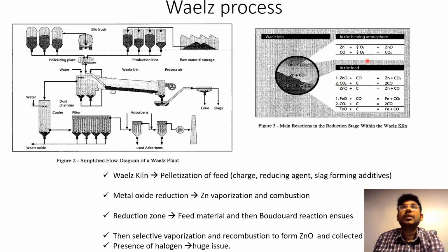With the temperature set around 1250 degrees Celsius, not a lot of other metals are going to be melted. So you have some formation of metals: zinc, lead, I think silver, cadmium, and all these things can be formed. Then you take it to a combustion chamber or the oxidation chamber, where you have the formation of zinc oxide, right? And then you can regenerate the CO2 and it can be used back again.